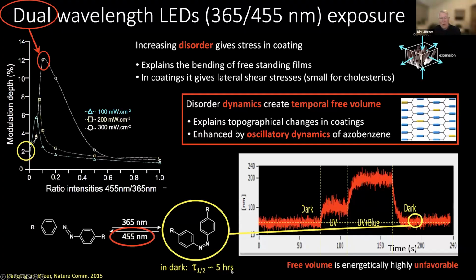The half-life of the azobenzene that we are using is in the order of 5 hours, while this transition from elevated to flat is occurring in a few seconds, just because the free volume is energetically highly unfavorable, and as soon as we are not actuating this anymore with the double wavelength exposure, the actuation of the volume formation is also lost.